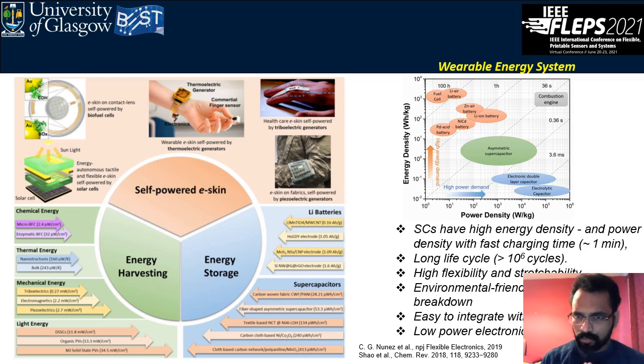To overcome this issue, there is major work going on recently on different types of supercapacitors. Supercapacitors can produce very high power compared to batteries, but the energy density of the supercapacitor is low. So various materials are now being utilized to improve the energy density of supercapacitors. The major advantages of a supercapacitor are very high flexibility and stretchability, a charging time of less than 1 minute, and a life cycle of more than 10 to the 6 charging discharging cycles.